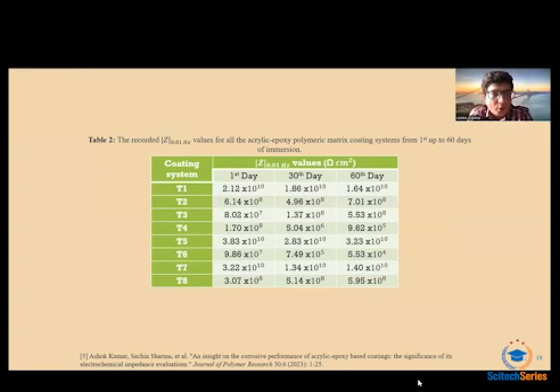So our focus would be on T1, T5, and T7. And let's look at T5, for example. The corrosion protection performance, or the Z impedance values, were seen to be maintained at an order of magnitude of 10 to the power of 10. Similarly, for T1 and T7, it's still maintained in the same order of magnitude.